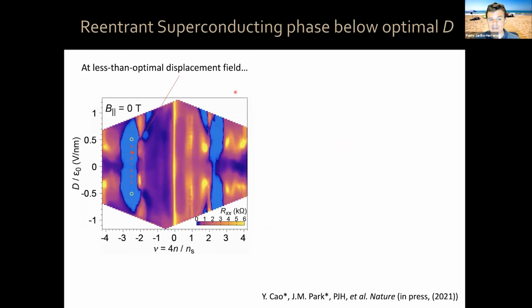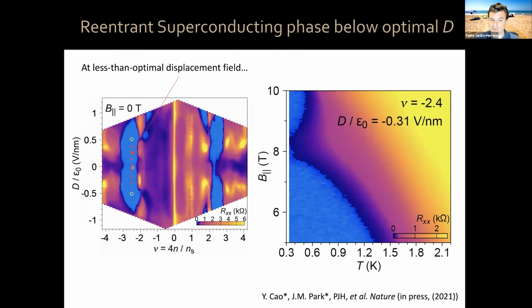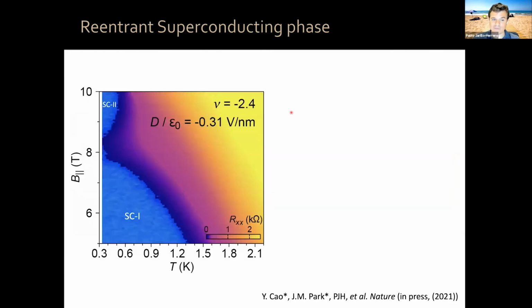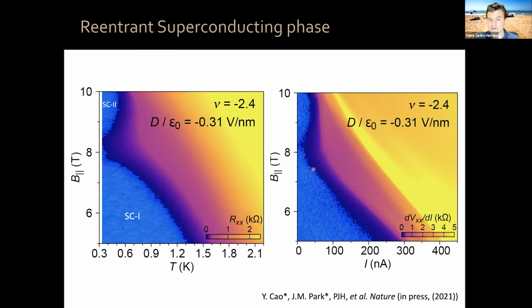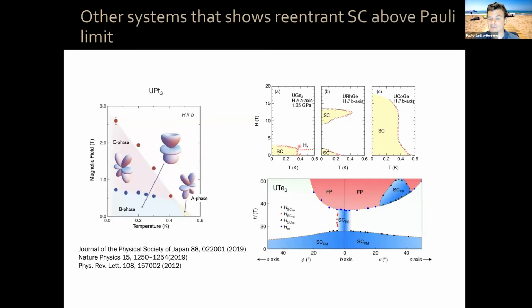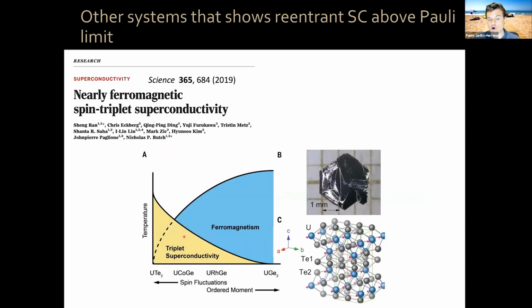Moreover, none of those mechanisms explain the fact that in other regions of parameters, at smaller displacement fields, we see reentrant superconductivity, okay? Your zero resistance region decreases with parallel magnetic field, but then at high field, it reappears again. That reentrant superconductivity, which we can see in the critical temperature or in the critical current, is extremely anomalous. It only happens in heavy fermion superconductors, with the uranium family of compounds, and especially uranium ditelluride recently. These are nearly ferromagnetic or actually ferromagnetic spin triplet superconductors, okay?